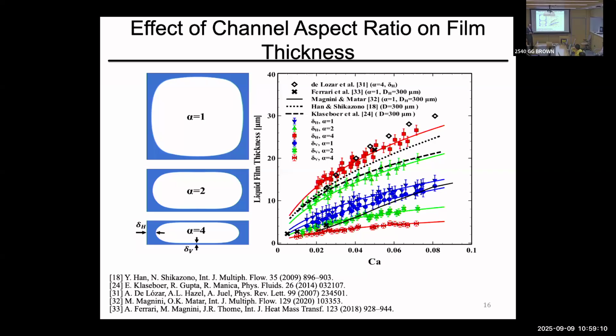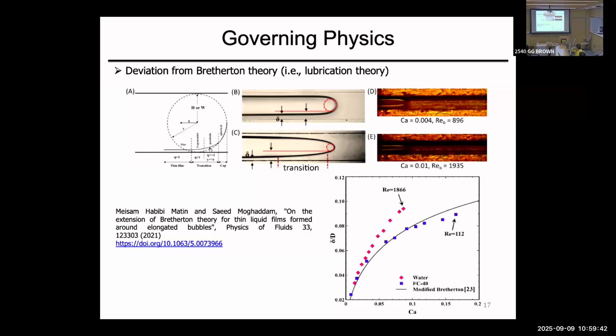So what happens when surface tension is actually squeezed? It pumps the liquid to the edges. So that's why it's much thicker there. And that was rather simple to model. It's fascinating modeling that you see efforts on, but rather possible to model analytically. And that's what we have. But the focus of this case was that we did the experimental data on this. We decided to focus on the delta. But his modeling applies even if the surface is heated and there's evaporation, is it still applicable?